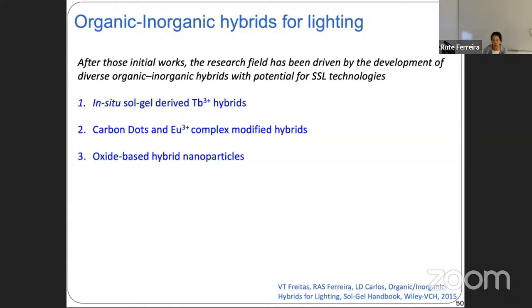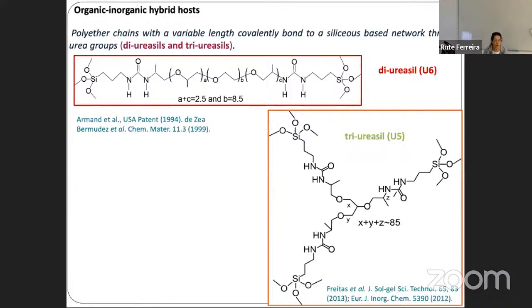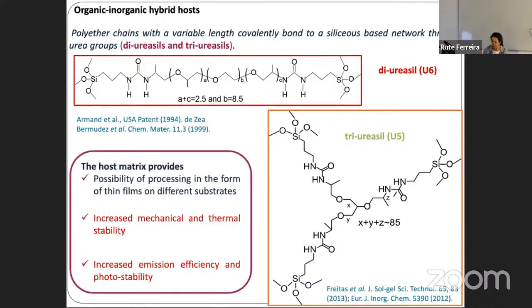So what are the organic and inorganic hybrids that serve as a host for the emitting centers? We typically select the diureasils and triureasils. They are made of polyether chains of variable length, in a linear or branched structure, that are covalently bound to a siliceous backbone through urea groups. The rationale for the selection of these hosts is that we have been demonstrating over time that, besides the possibility of processing the final materials in the form of thin films on virtually any substrate, they provide increased mechanical and thermal stability, and they also increase emission efficiency and photostability.